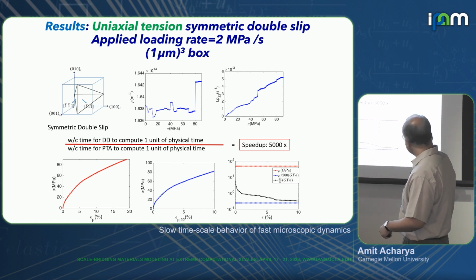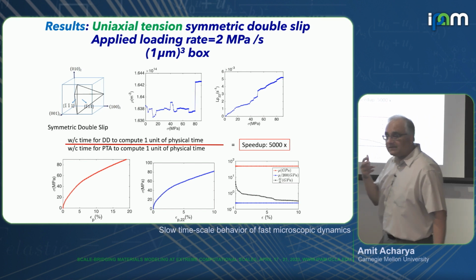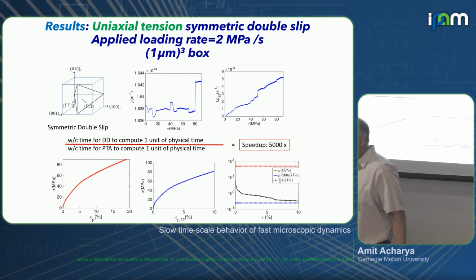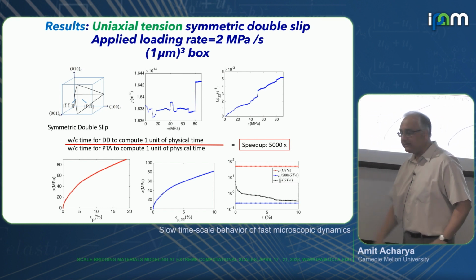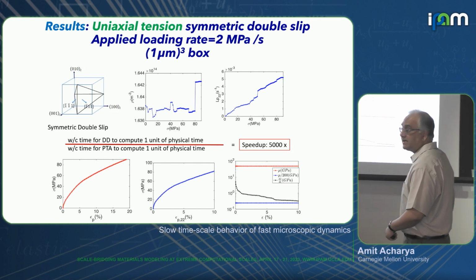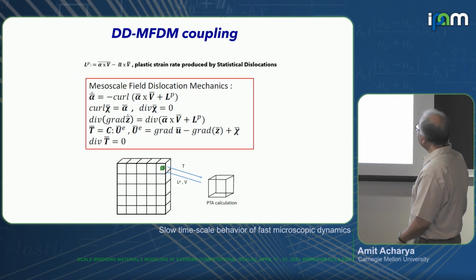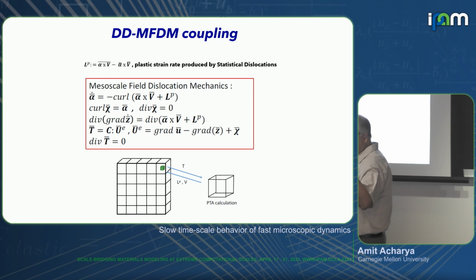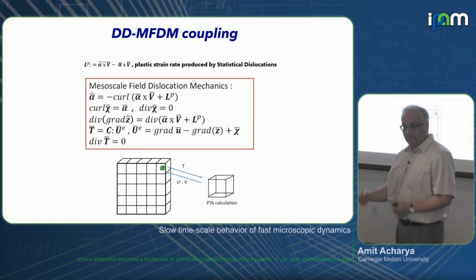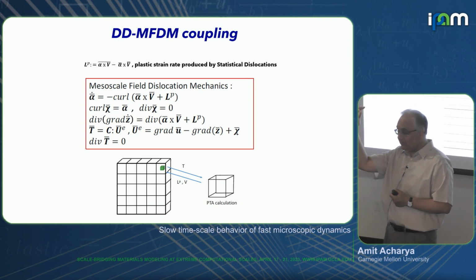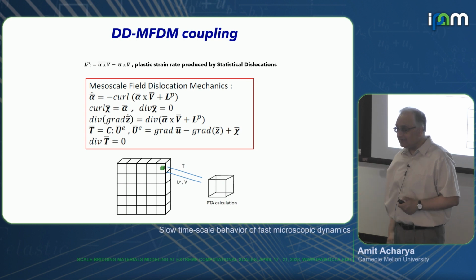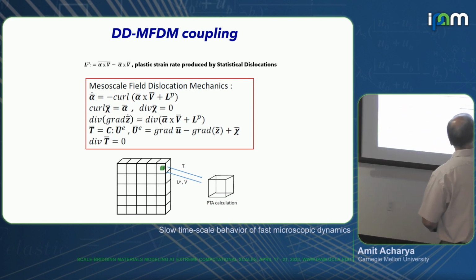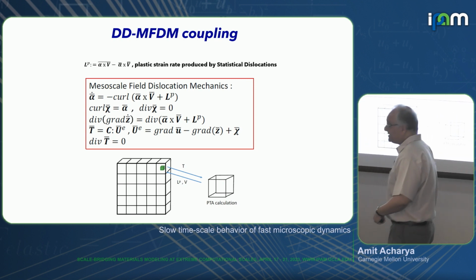The hardening modulus, experimentally it's known that you get up to the shear modulus divided by 200. It does come down to that. And then we coupled, remember the PDE model that I was talking about? There it required an input for the LP. So the idea now is that this LP is going to be fed in.